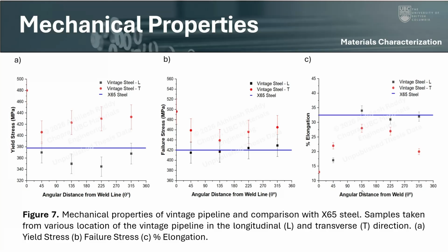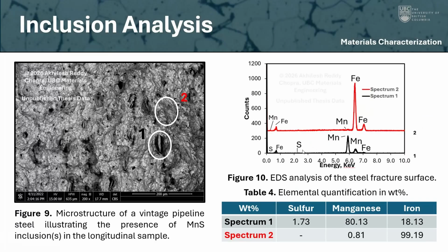of the material. And so we can see orientation dependent properties based on hypothesized orientation of MnS inclusions. So this is very interesting information. And I confirmed the presence of MnS inclusions from doing EDS analysis on the fractured surface.